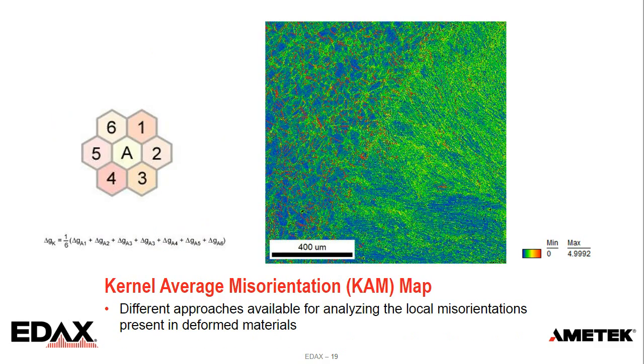We can also measure local misorientations, and it's a little tricky how we choose to describe this. Sometimes it's termed strain. It's really not strain, but that's what it's called, or plastic strain. But essentially, as we permanently deform a material, it introduces misorientations. And if these misorientations are large enough to be detected with EBSD, we can count them.